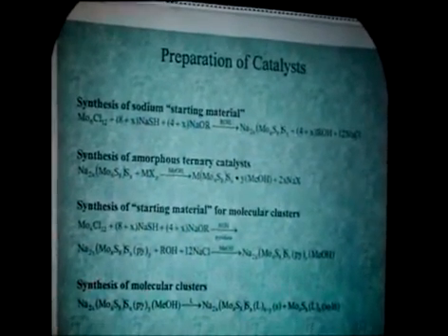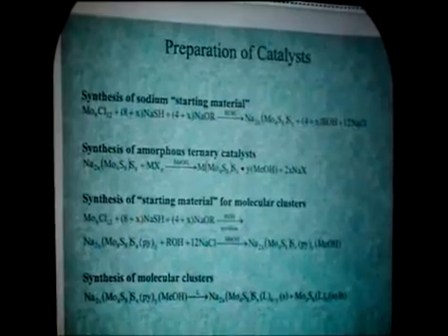If you want to produce these ligated molecular compounds, you can produce those as a ternary compound, but you can also produce the single molecules. What you do is add the ligand to the first reaction, and you form a ligated sodium-containing amorphous material. If you reflux that in excess ligand, you can actually obtain and isolate soluble single molecules.